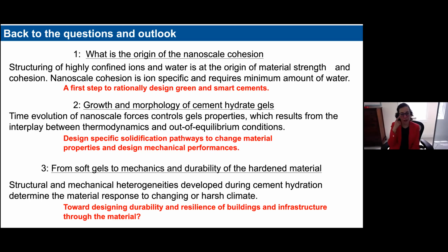What I showed you is that, in fact, if we start to approach with a physics perspective the cohesion of the material, we can understand that water plays a very important role, and we can understand quantitatively the ion specificity of the nanoscale cohesive forces in cement, and how the evolution of the forces depends on the water confinement and on the ion water structuring. And I would say that this is really a first step, maybe the zero level step, to now design cements that are greener and can still perform in a similar way.